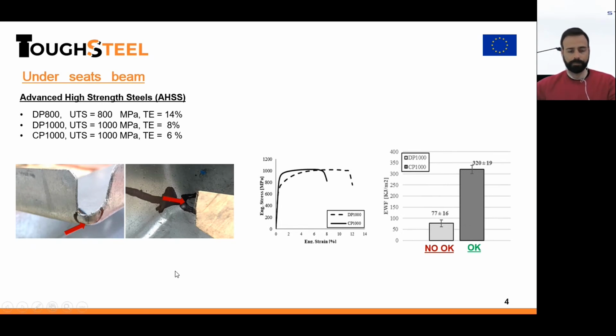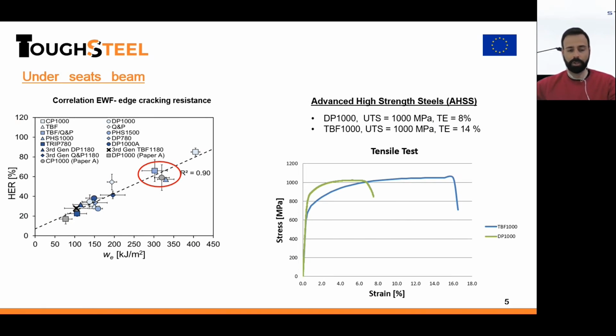In the meantime, for the innovation, and also to reduce the weight of the component and to assure more complex geometry, we studied different materials together with Eurecat. This is the graph that David showed before, in which there is the correlation between the hole expansion ratio and the work of fracture, in which we can see there is a direct correlation between these two kinds of measurements. For this reason, taking into account the experiments done in the different European projects, we put our attention on the material highlighted in red in this graph.